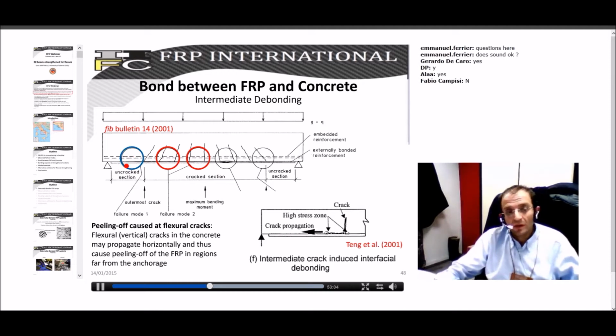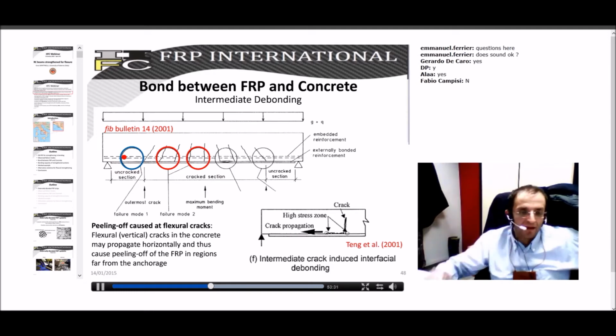So if you want to evaluate how much is the strength of this final part of the strip, you have to consider what is the bond length, which is basically the length between the last bending-induced crack and the cutoff section. If this is lower than LE or higher than LE, you can evaluate what is the maximum force you can potentially apply here, or what is the corresponding strength you can mobilize in this point.